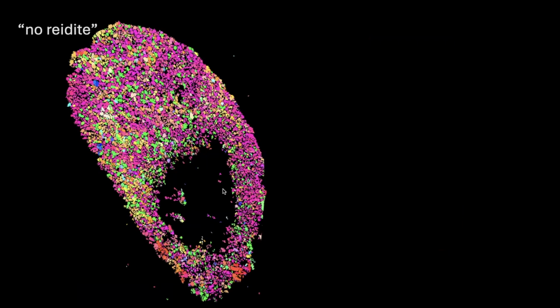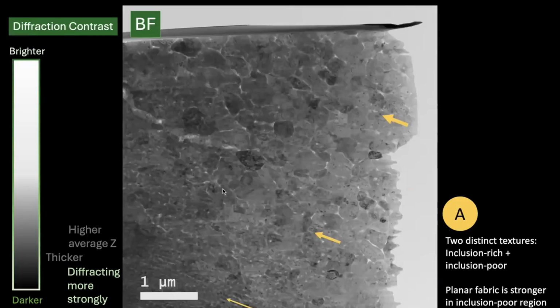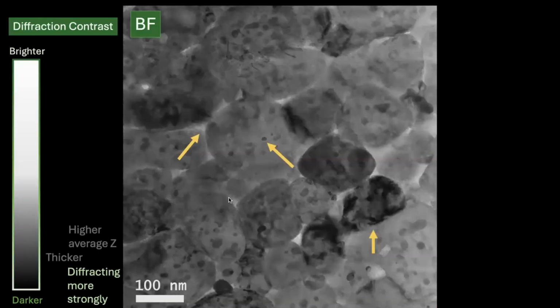The other grain, the one that had no Reidite, this one is definitely more complicated. So here's what it looks like. We kind of have two distinct textures. There's an inclusion-rich area and an inclusion-poor area. And there's a planar fabric that's stronger in the inclusion-poor region. So I'm going to talk about the inclusion-rich region first. Here's what it looks like in that bright field TEM. So remember, this is mostly diffraction contrast. We have many inclusions inside of the granules, and there's high strain in some of the granules. But besides those inclusions, like not too much strain.